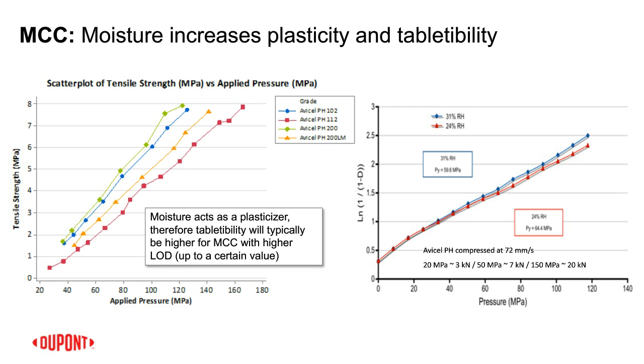The smaller particle size is going to give you a better compactibility because it has a higher surface area, right? So in a formulation, when you have diluted with other particles surrounding the MCC, that's where the particle size and the surface area start to play. So typically with a smaller particle size Avicel grade, you're going to have a stronger binding capability, a higher dilution potential, because it has a higher surface area.